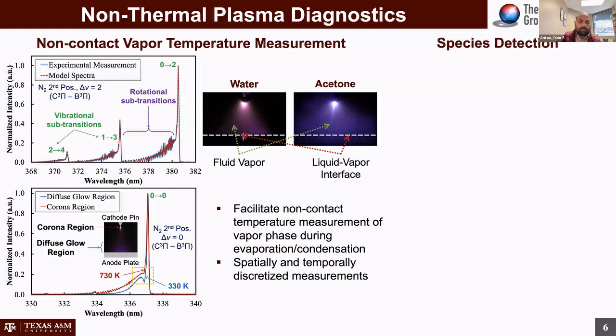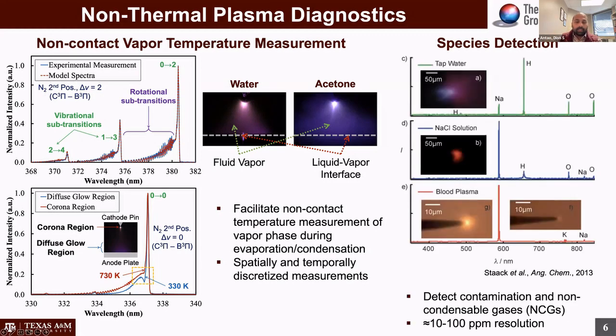Something else that you can do with these plasmas is, because they emit light, and the light that they emit corresponds to the species that's emitting the light, you can detect the type of species that exists within the plasma. And again, the key here is using these non-thermal plasmas. Now we're looking at doing pulse plasmas in the 10 to 100 nanosecond duration scale. That time scale allows us to operate the plasmas, for example, in water without electrolysis, essentially, and without thermalizing the plasma.